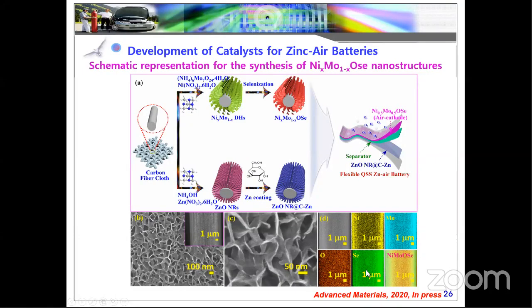These elemental distributions are confirmed by SEM EDS analysis: nickel, molybdenum, oxygen and selenium are uniformly, homogeneously distributed over the area. From the studies, we conclude our material contains nickel, molybdenum, oxygen and selenium.